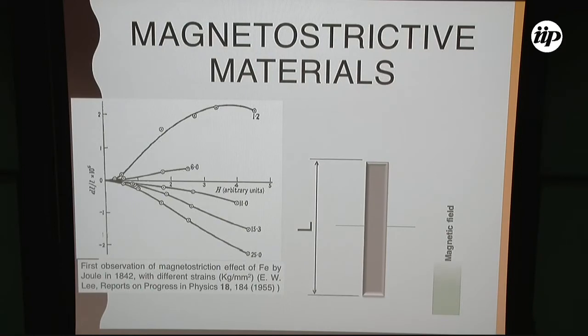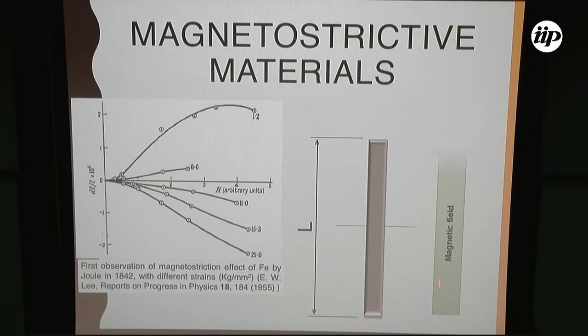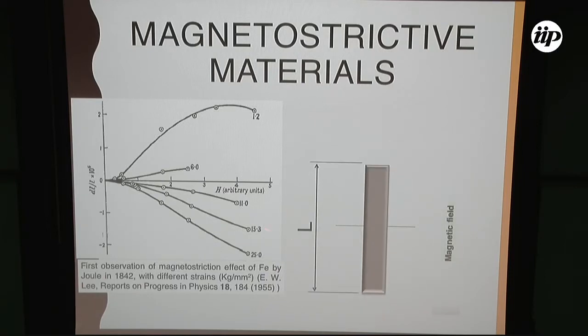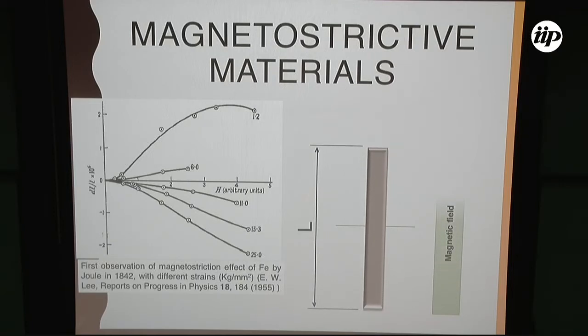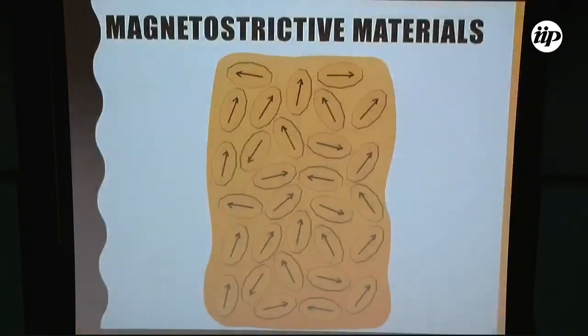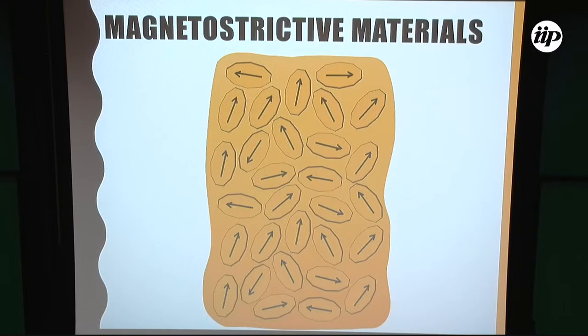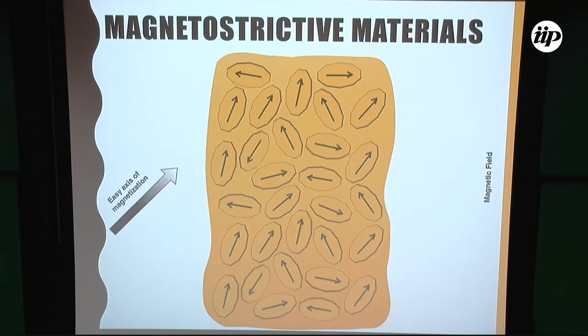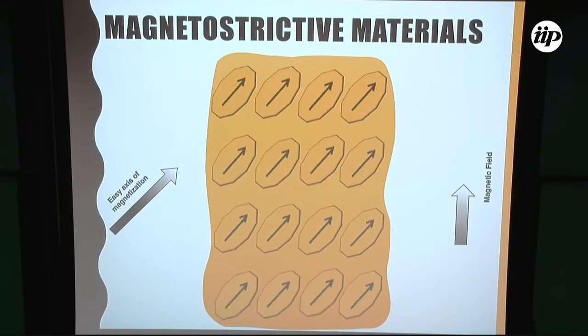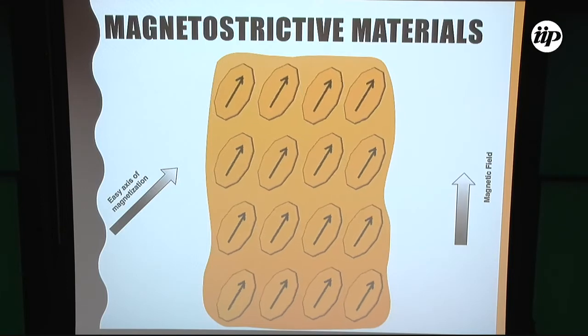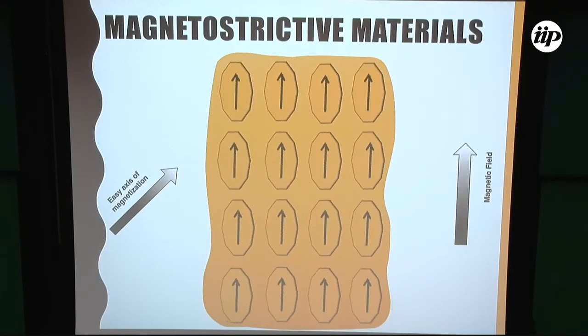Magnetostriction is an old phenomenon, observed by Joule in the 19th century. When a magnetic field is applied, the magnetic material changes its size in a direction, for example increasing the length of the material. From the point of view of the magnetic domains, it depends on the applied magnetic field, which changes the magnetic domains toward the easy axis of magnetization. When the magnetic field increases, the direction of the magnetic domains changes.